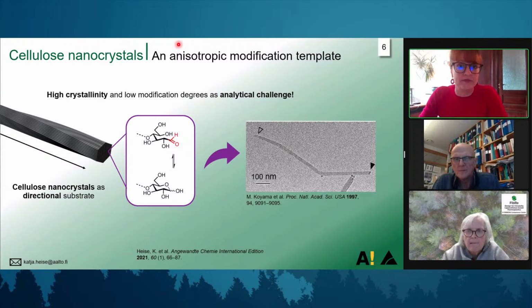What we observed is when you have protonated sulfuric acid half ester groups, then you have self-hydrolysis of the cellulose from a temperature of 50 degrees on. This is really problematic, especially for me, because I use them freeze-dried and I redisperse them. It's impossible to properly redisperse protonated sulfuric acid hydrolyzed cellulose nanocrystals. Okay, thank you for the answer. So ion exchange is really the safe bet there. I would always ion exchange them if you plan to try them.